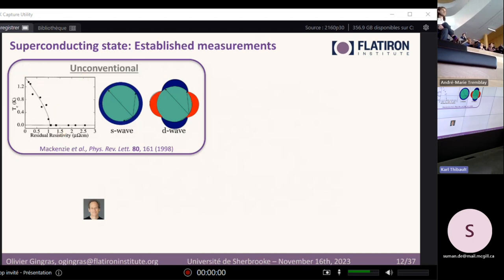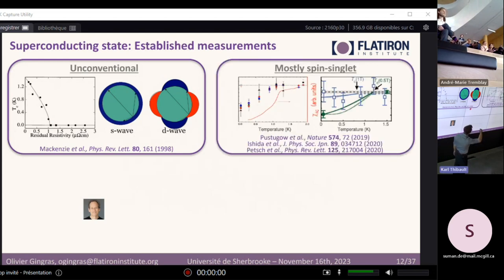This is an indication that, when you add non-magnetic impurities, you will average all the states of your gap on your Fermi surface. So if you have a sign-changing gap with nodes in particular, then this averaging will lead to zero very quickly. That's why such behavior with non-magnetic impurities is considered to be a signature of unconventionality. Another important aspect of strontium ruthenate is the spin singlet dominated composition of the Cooper pairs.